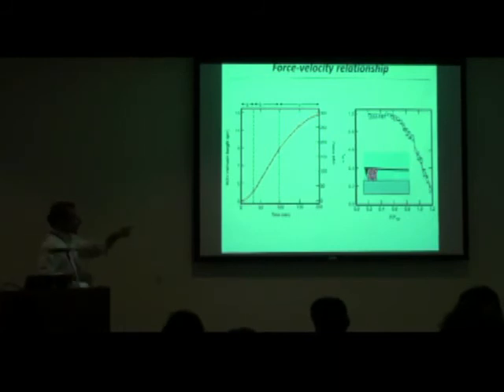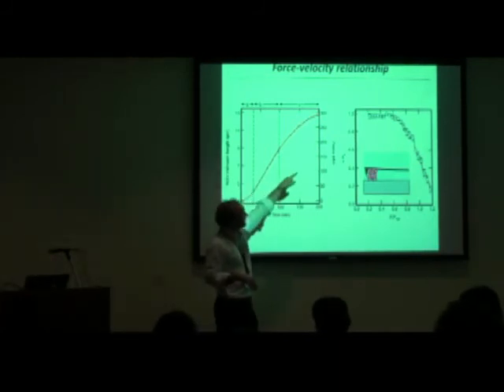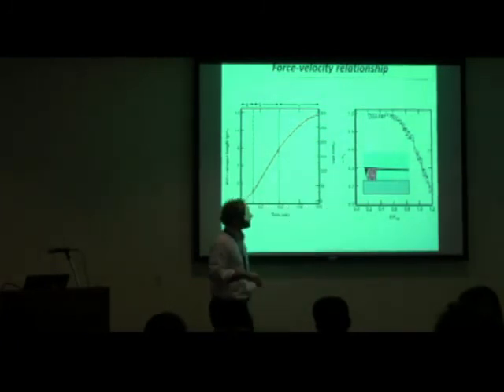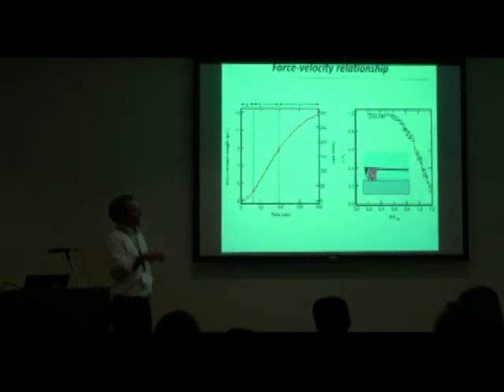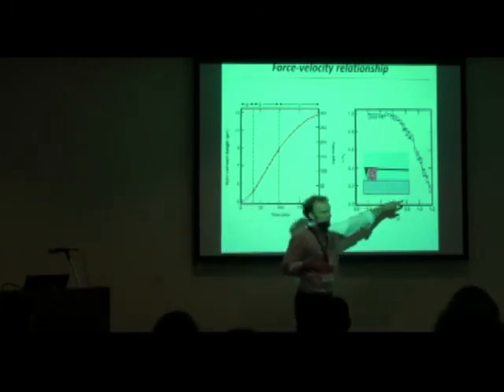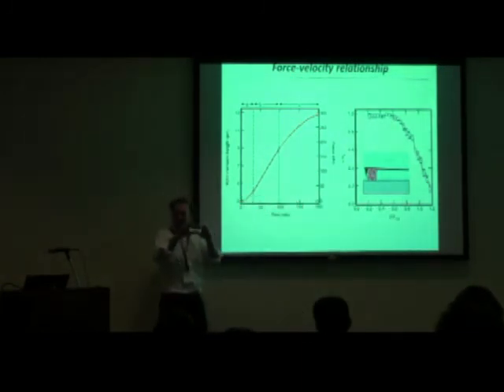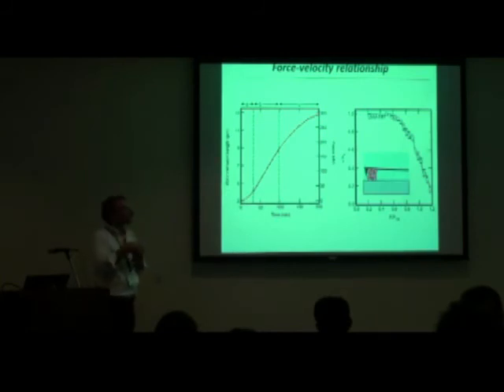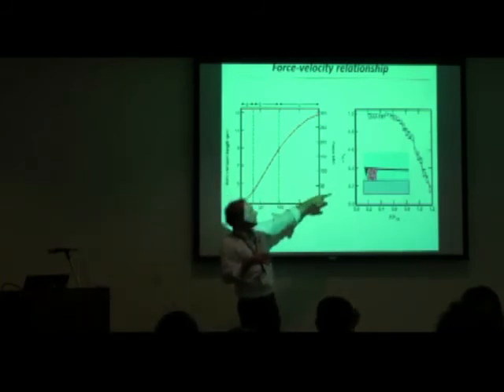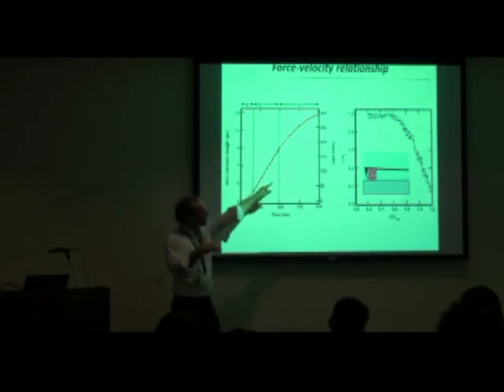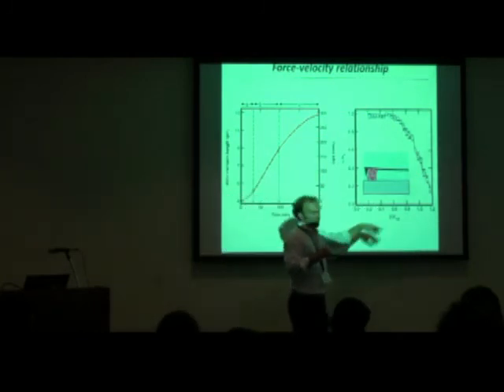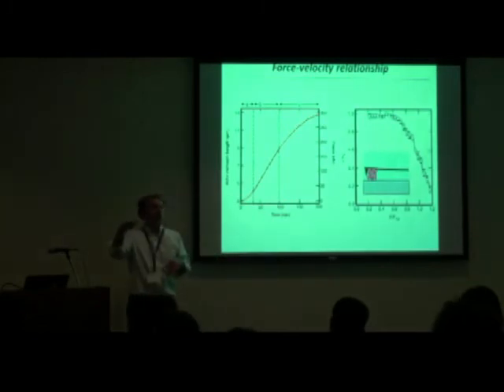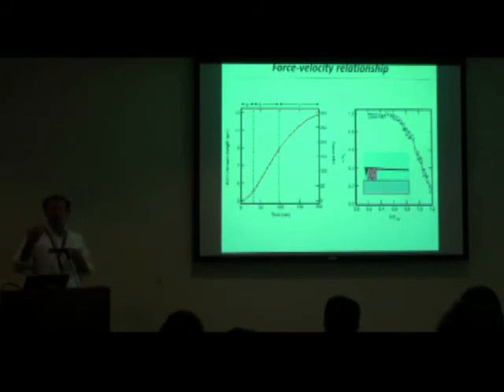And so if you take the growth curve, it looks something like this, and you plot it as a function of velocity and force. What this is saying is that at some point, if I push hard enough, I can stall the growth. This network can't keep assembling if I push hard enough. But if I don't push quite as hard, I'll go faster. And over some range, that's about half of this force-velocity relationship, I get a constant growth rate. That is, I'm growing at a constant growth rate. I'm adapting to this force. I'm not slowing down. So what could be responsible for that?